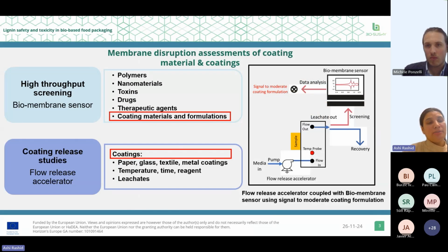So the membrane disruption assessment of coating materials and the resultant coatings are performed using an innovative mini flow release accelerator, which is coupled with the biomembrane sensor. And in the first step of the membrane disruption assessment, coating materials are screened using a high throughput screening technology, which is based on a biomembrane sensing platform. This biomembrane sensor is very sensitive and responsive to the presence of small amounts of different materials ranging from large size polymers to small size nanoparticles, nanoclusters, from toxins to useful therapeutic agents like peptides and drugs and different coating materials and formulations.